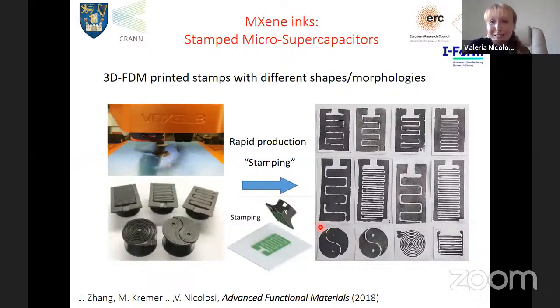And we did take advantage of these inks that were so easy to manipulate. For example, we wanted to really test the capabilities of these inks in a very, very fast way. So what we did was we built a lot of different stamps by 3D printing, normal fused deposition modeling stamps. And that allowed us to build these stamps with all different geometries, and we like a lot interdigitated geometries like these ones, because it allows us to maximize the surface in contact with electrolyte and therefore increase the capacity that we can get. So, all you can do once you get the stamps is dipping the stamp onto the ink and then really stamping away on any sort of surface.